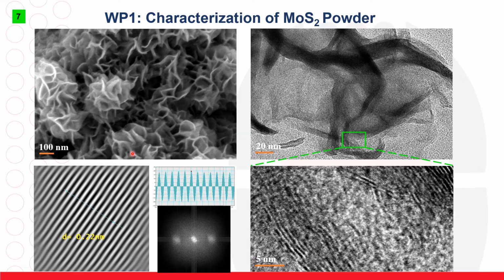And characterization using the scanning electron microscope revealed the flower-like structure of molybdenum disulfide, and this is typical for molybdenum disulfide according to other literature. Observation under the transmission electron microscope showed thin petals of molybdenum disulfide, and obtaining high-resolution images revealed a d-spacing of 0.22 nanometers for all samples.